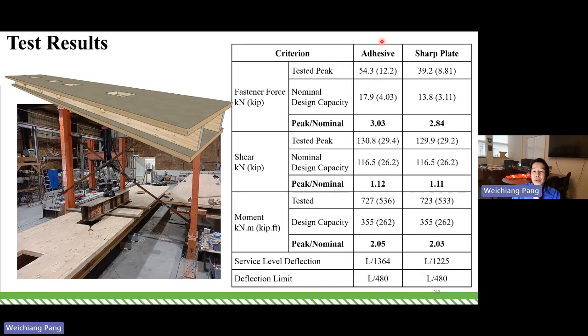So this shows the summary test result for the structural adhesive using screw and adhesive, and then sharp metal plate, both with screws in them. This is the back calculated force, what we think the force inside the connection is, the tested load, and the nominal design, the hand calculation, the engineering design. So the peak load versus the nominal calculation, the ratio is about 3.